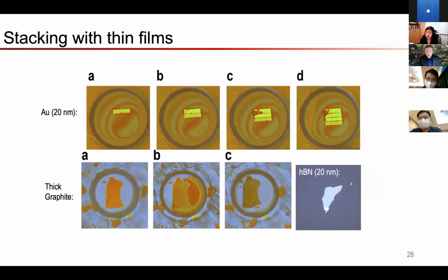That's one way to address this. Nevertheless, I will also show some images of thicker films that we've picked up. You can see here that although near the edges there's a little bit of wrinkling in some cases due to the uneven initial contact, the films overall survive pretty well. Again, if we can achieve perfect coplanarity between the two surfaces via active in situ measurement, we should be able to resolve this issue. So yeah, I think you're totally right. This is something we're really acutely aware of and we hope to solve in the future. Yeah, thank you, Professor.